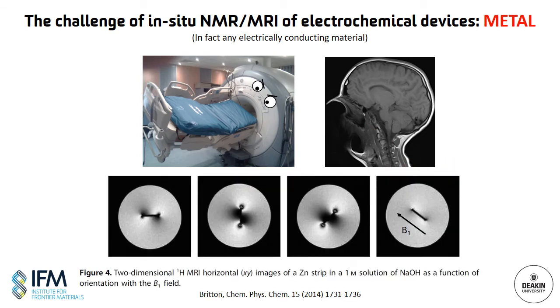Fortunately, it's quite simple for a cell design such as this, because if the metal electrodes are parallel and flat, it's possible to largely eliminate these distortions by aligning the surface of the electrodes with the RF field. And this can allow you to obtain images from the electrolyte right up close to the electrode surface. And that's where the reactions are happening inside our thermocells, so that's really important.